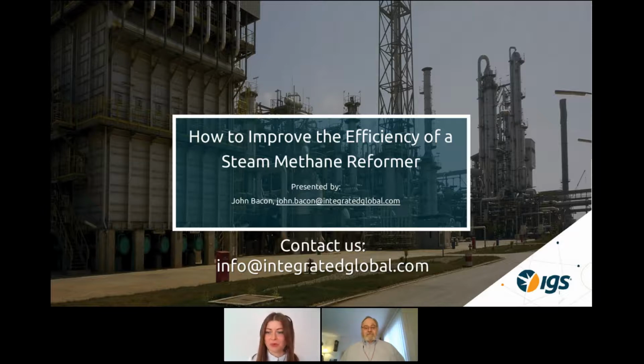In primary reformer refractory is more than 20 years old. In this case, would the thermal emissivity coating be effective or not? Well, we'll increase the emissivity, yeah, whatever condition or whatever the age of the refractory. But we'd like to have a sound base to apply the coating to. So the first thing we do whenever we go inside a unit is look at the condition of the refractory. If we feel that it's good enough after cleaning to apply the coating, then we'll go ahead.